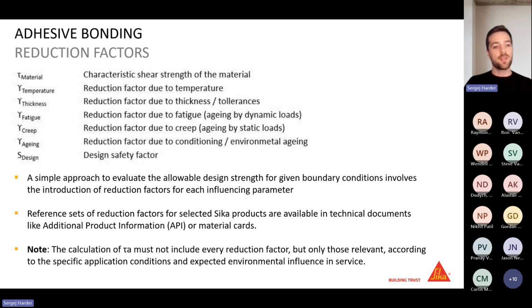For a lot of these adhesives that we use, we have the so-called additional product information. So for example, also for the adhesive that I will show you for this cap concept, we have this short API where we gathered a lot of testing data, also with artificial aging conditions, where we can show that after a certain aging, this will be the reference strength that you will still have. So we have quite some substantial data to check, and also maybe derive these reduction factors for your design.